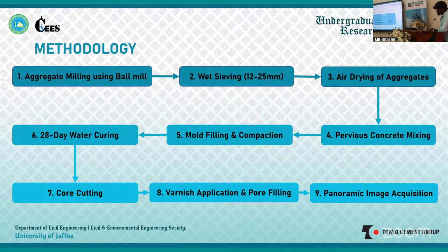First, aggregates were subjected to 3 different abrasion levels: 0, 200, and 1000 revolutions. After abrasion, the aggregates were wet sieved to obtain the required size range of 12 to 25 millimeters and then air dried. Next, pervious concrete specimens were prepared using 3 aggregate to cement ratios of 3, 4, and 5. A water to cement ratio of 0.3 was maintained to achieve a zero slump concrete mixture.